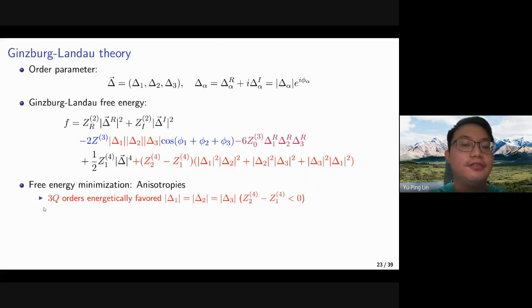And the free energy minimization to distinguish the ground states is done by identifying the anisotropies. So the first anisotropies to look at are the red ones. We can see that the 3Q orders are energetically favored. That is, if we have a finite magnitude for the order parameter vector delta, we should have delta 1, delta 2, delta 3 to be equal, so that we could maximize this term. And also at the quartic order, because this one is negative, to minimize this term, we should have them to be equal to each other.